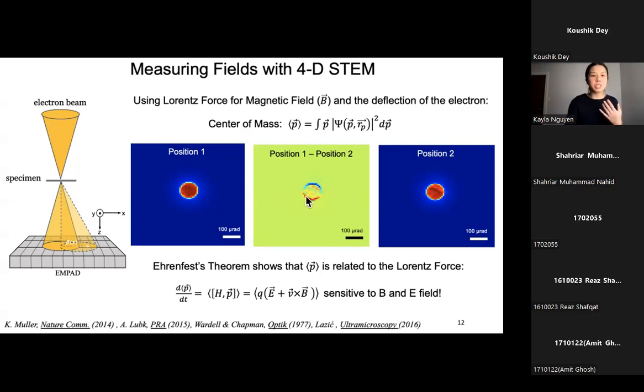Right. So this is just a visual to give you an idea of how the magnetic field changes in the electron microscope. Technically, mathematically, what I'm actually doing is calculating the center of mass of each diffraction pattern. As you're scanning your image, you get an electron diffraction pattern from each position. Each diffraction pattern gives you the center of mass, or the expectation value of momentum. And mathematically, I'm applying this equation to get back my magnetic field. So this visual is just showing how the magnetic field can change from one position to another because of the deflection. It's just a visual. But mathematically, I'm utilizing this Ehrenfest theorem.